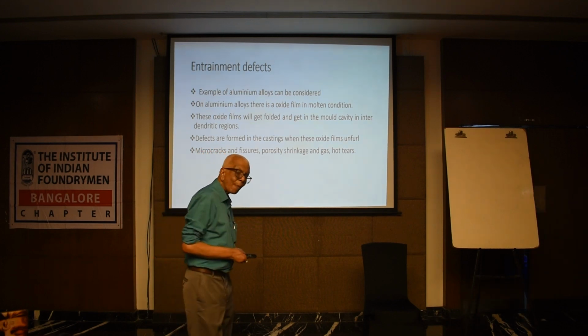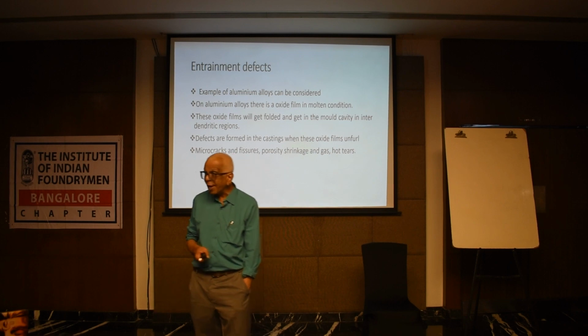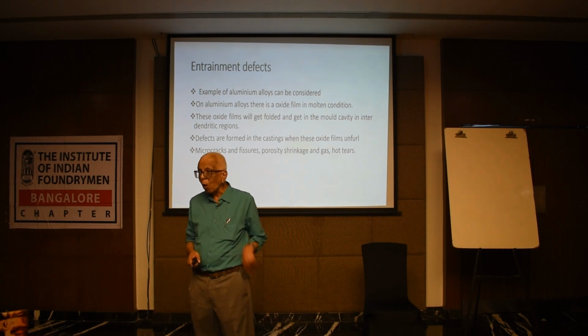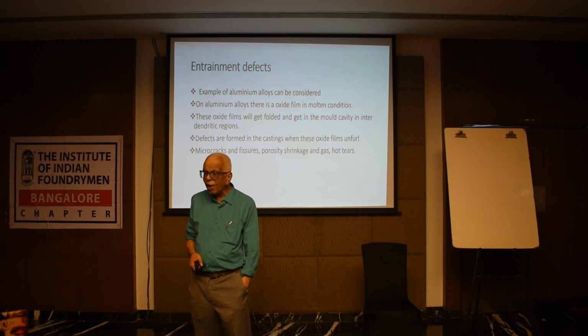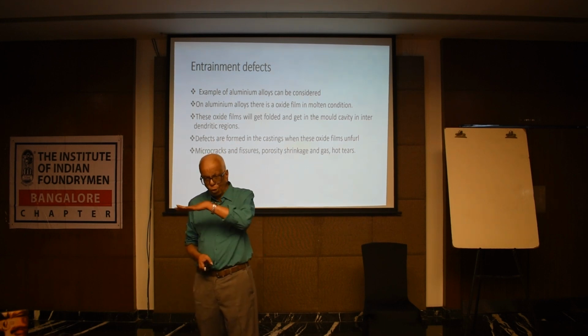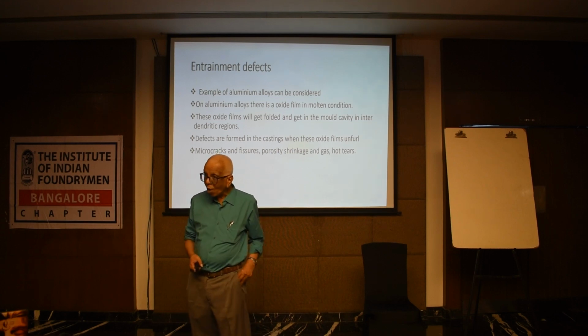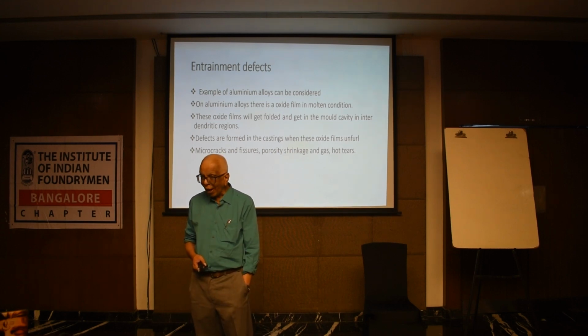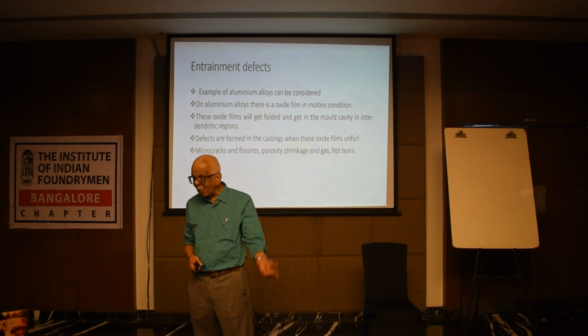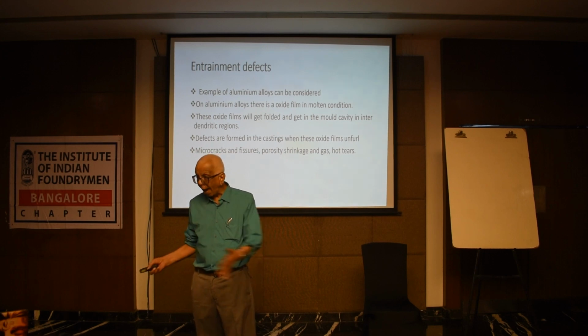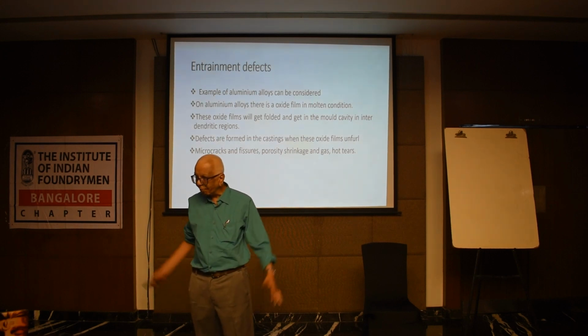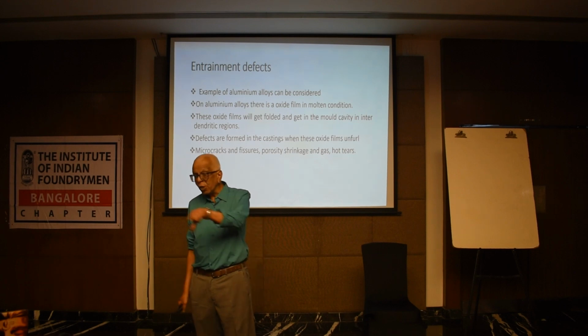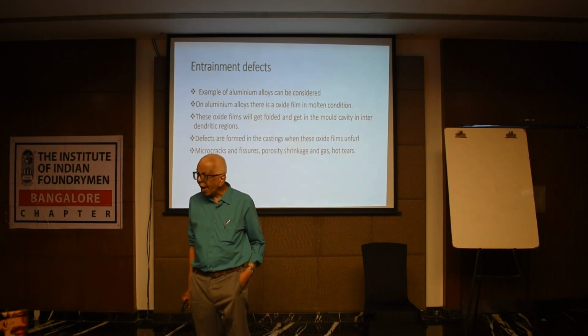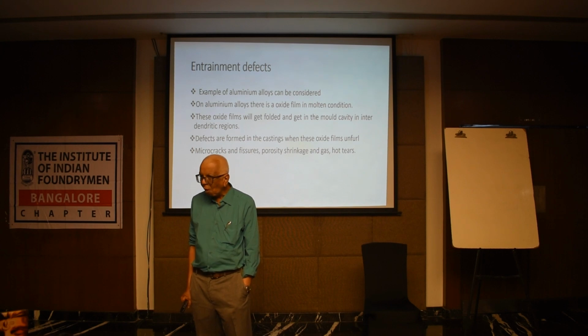Entrainment defects. What are bifilms? First of all, let me explain with you what bifilms are. In aluminum alloys, for example, when you melt aluminum, you have a surface oxide film, aluminum oxide. That oxide film, when you pour into the mold cavity, gets folded up. It's called furling. They furl up and get entangled in the interdendritic areas of the casting.